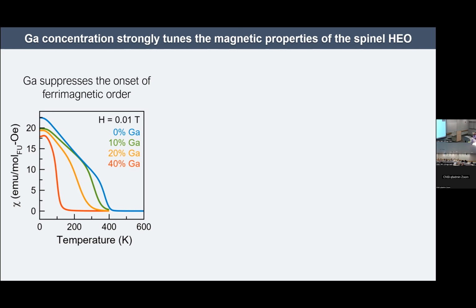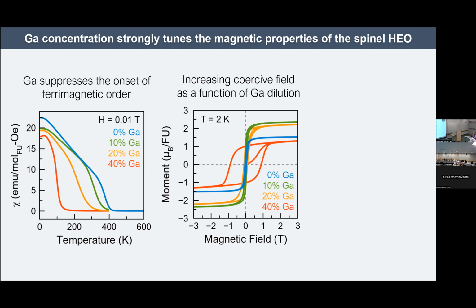It's only 4 compositions, but it is nice to know that when you actually plot this on a graph, TC versus gallium, it is exactly linear. So I don't know if that extends all the way down to 0. And then when we look at magnetization, we can see something a little bit less trivial is taking place.